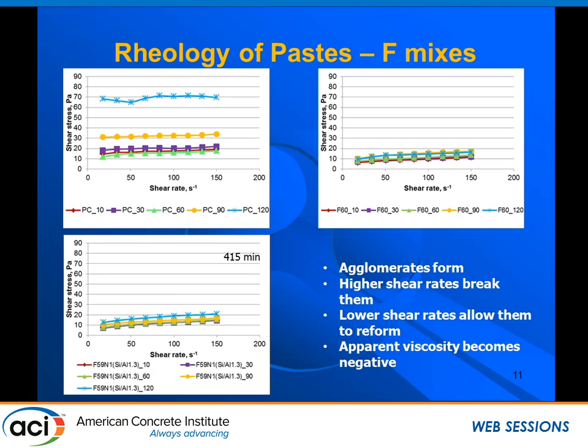What's going on? We believe agglomerates are forming, and as we increase the shear rate, we break those agglomerates. When we decrease the shear rate, these agglomerates are capable of reforming. So we get a negative slope, giving an impression of a negative apparent viscosity, which isn't possible. We're really just seeing agglomerates forming—something in the microstructure is changing.